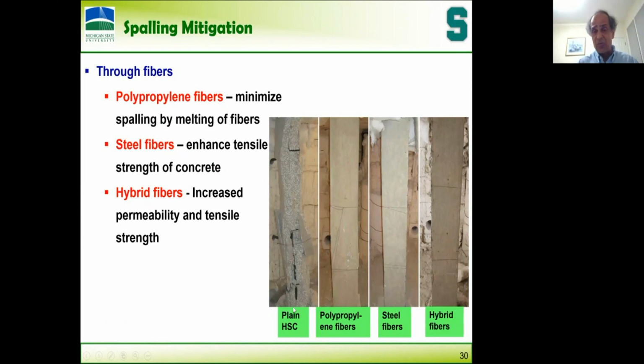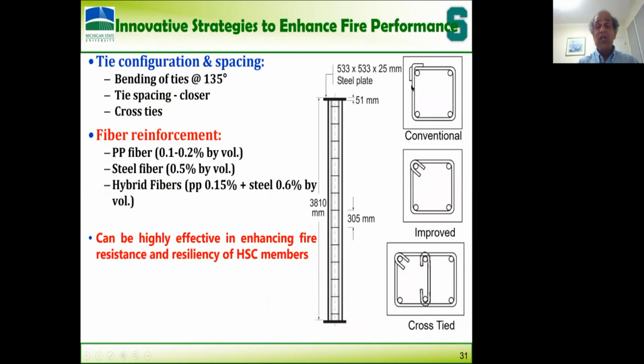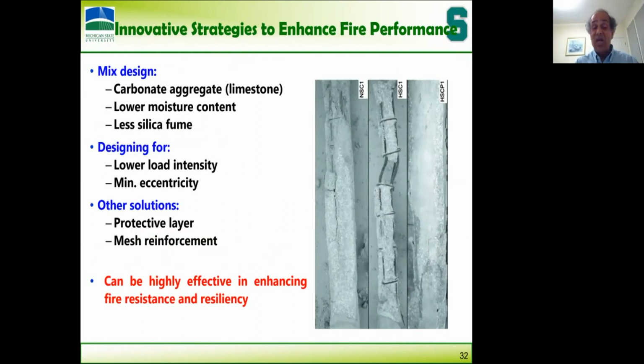So look at the columns we tested. These are all tested in the lab. Plain concrete, polypropylene fibers, no spalling, steel fibers, very little spalling, as well as hybrid fibers. You can change the configuration. If you provide the ties like this, it does wonders. It increases the fire resistance. Instead of failing this column in fire at 1.5 hours, it can go up to 4 hours by just bending these ties or by providing cross ties. Okay, and there are very minor other things like changing the aggregate and stuff. I'm not going to get into this.